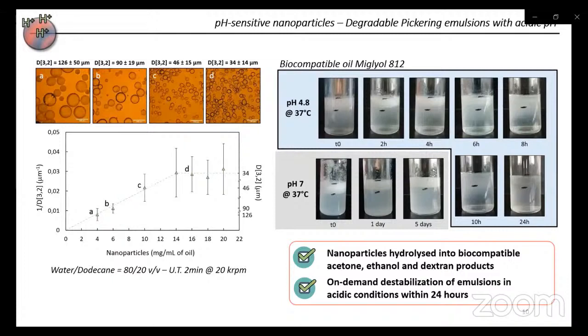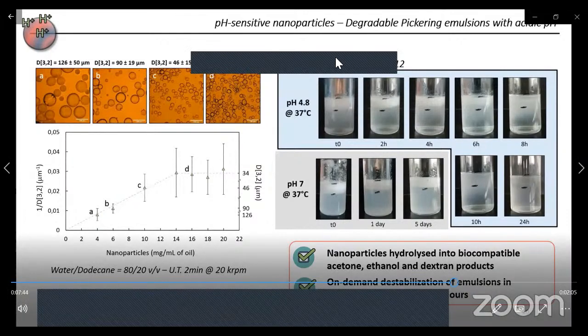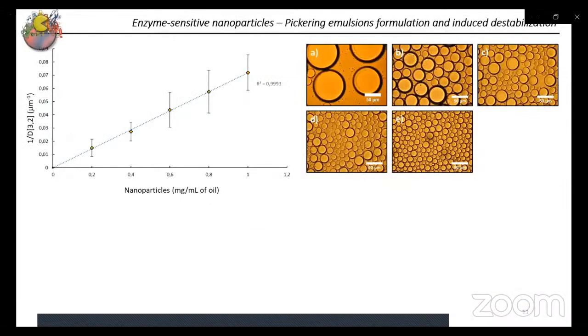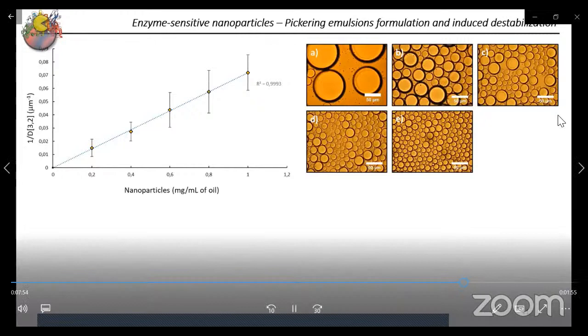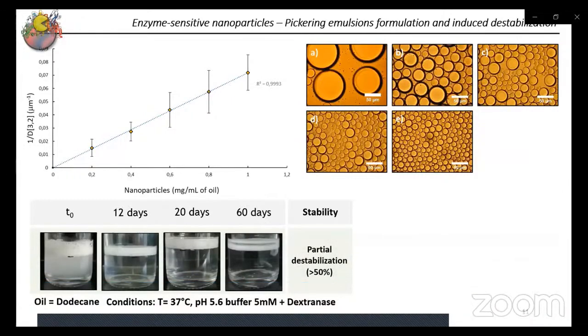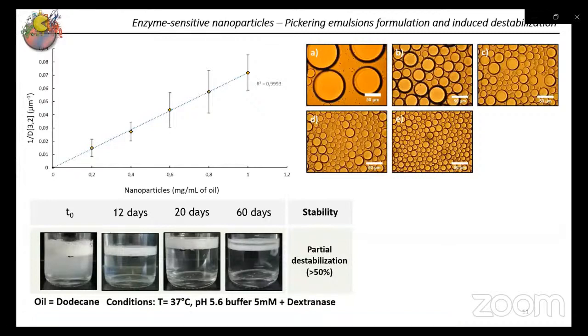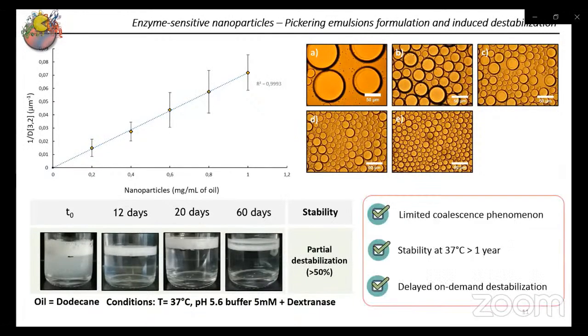So this system is quite interesting because it is biocompatible, as the hydrolysis of the nanoparticle produces acetone, ethanol, and dextran, and within 24 hours we are able to fully destabilize the emulsion. Finally, with the enzyme-sensitive system, we can still stabilize the Pickering emulsion and observe the limited coalescence. We were also able to partially destabilize an emulsion within 60 days, but this can maybe be improved by playing around with the pH and the amount of enzyme we put. And these emulsions are really highly stable, as they can be stable for more than a year at 37 degrees.